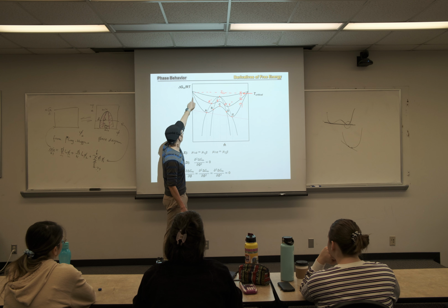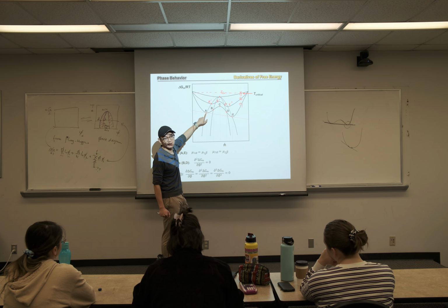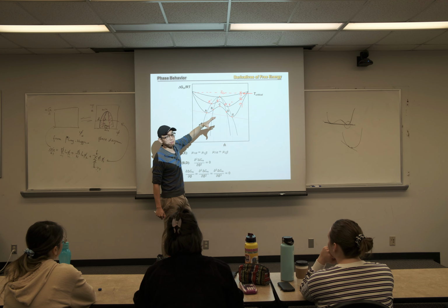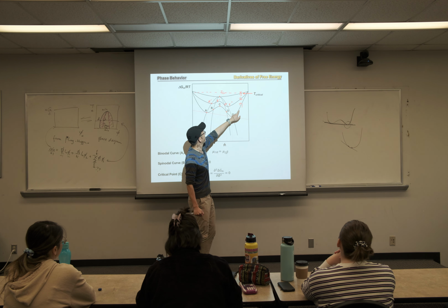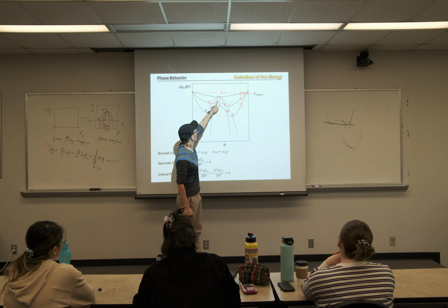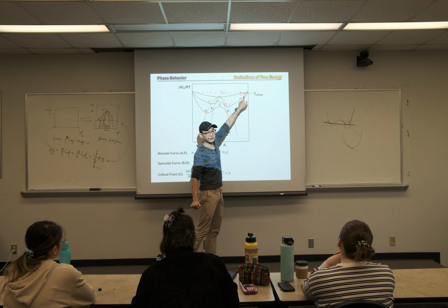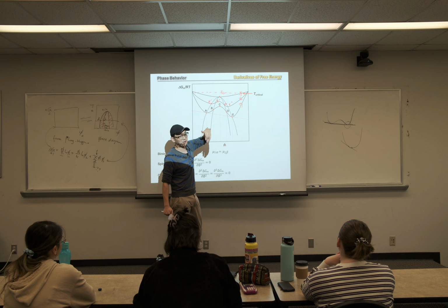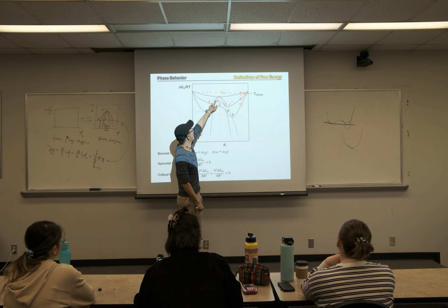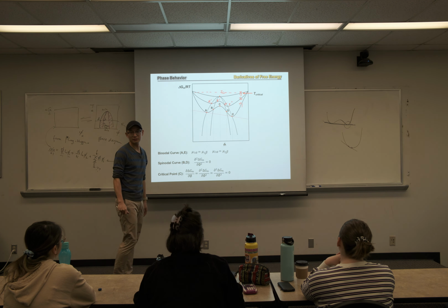So look at this black line. This would be at a given temperature T1. But when you change the temperature, your delta G shape will change. So when I raise the temperature, my delta G dependence on phi could change into this particular curve. And if I keep changing the temperature, your contribution of enthalpy and entropy will slightly change. So eventually, you will reach an always stable state.